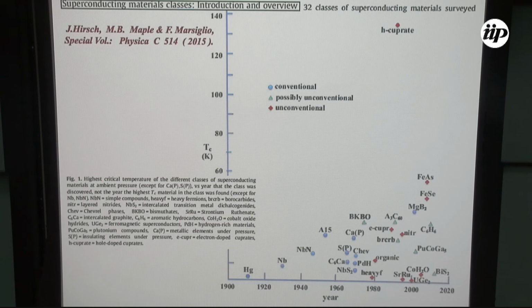This is a nice picture from a review on superconductors by Hirsch, Maple, and Marsiglio, 2015, where they surveyed 32 classes of superconducting materials and classified them depending on whether there was evidence for the mechanism of superconductivity to be conventional, possibly unconventional, or unconventional. As you see, here you will find, for example, the pnictides and the cuprates, and down here in 2015, they put bismuth S2 compounds as possibly unconventional. They more or less remain in that category, although there is more evidence that electron-phonon coupling is not strong enough, so they are now more than possibly unconventional.